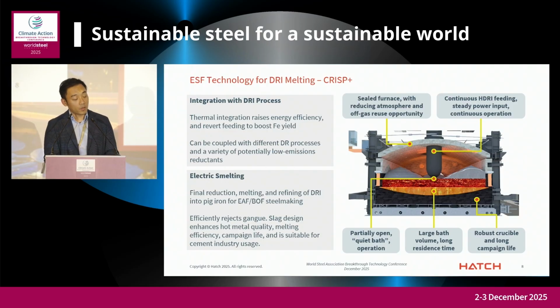So some features of the furnace: again, we say ESF and EAF are just one letter different, but the furnace looks completely different and operates more like a blast furnace and not an EAF. It's a stationary large furnace with 6 Soderberg electrodes. The roof doesn't open; in fact, it's very well sealed. It runs a very strong reducing atmosphere, with a very robust crucible that lasts a very long campaign life, comparable to a blast furnace. In fact, for one of our electric furnaces, the longest campaign life today is approaching almost 50 years, a single campaign for the electric smelting furnace hearth. So they do last a long time, unlike EAFs.